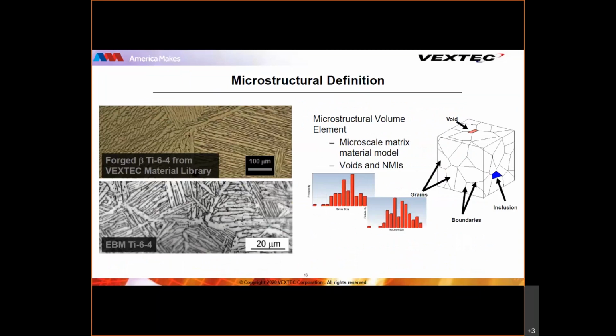And go to the next slide. And we've also noticed a lot of similarities with actual forgings, because we've kind of found that the difference between a conventional process metal and AM metal can be captured through the quote-unquote microstructural definition. And here's a case where we've got a beta annealed forged Ti-6-4 from our material library, and it has many attributes similar to an electron beam melted AM Ti-6-4.